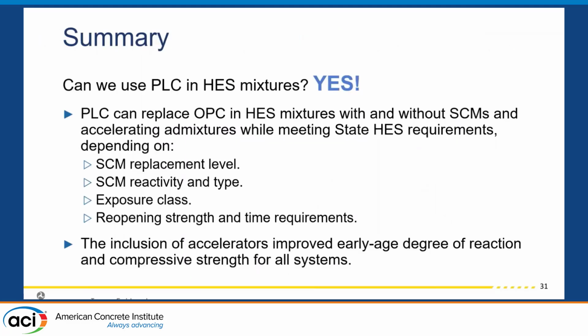But in summary, can we use PLC in high early strength concrete mixtures? Yes, yes we can. Our PLC can replace OPC in high early strength mixtures with and without SCMs and accelerating admixtures while meeting state high early strength requirements. And this depends on SCM replacement levels, SCM reactivity and type, exposure class, reopening strength and time requirements, and the inclusion of accelerators can improve early degree of reaction and compressive strength for all of these systems.